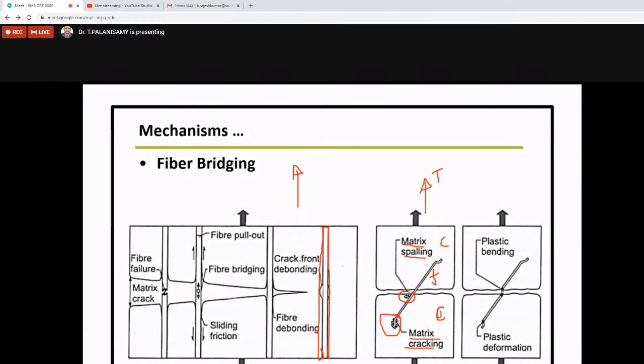First one is crack front debonding. This area tends to debond due to the load. Why does the crack not come here? Because this area is the weakest zone, and the crack always propagates through the weakest zone. This area is very strong, so the crack propagates in this direction. This area may be the weakest, so it starts here. Then crack front debonding starts, then fiber debonding starts. Fiber debonding means the bond between matrix and fiber is debonded.